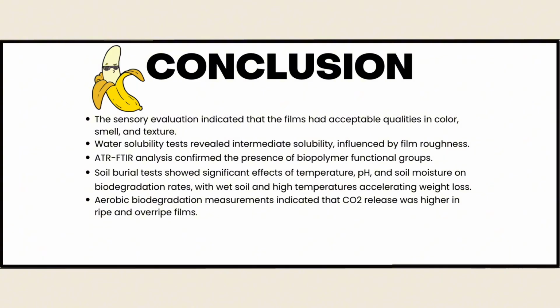To conclude, our study on banana peel-derived bioplastics yielded several key findings. Firstly, sensory evaluation showed that the films had acceptable qualities in terms of color, smell, and texture, making them a promising candidate for bioplastic applications. Next, the water solubility test revealed that the films exhibit intermediate solubility, largely influenced by the roughness of the film surface. The ATR-FTIR analysis confirmed the presence of biopolymer functional groups within the bioplastic material, validating that the bioplastics are indeed biodegradable.